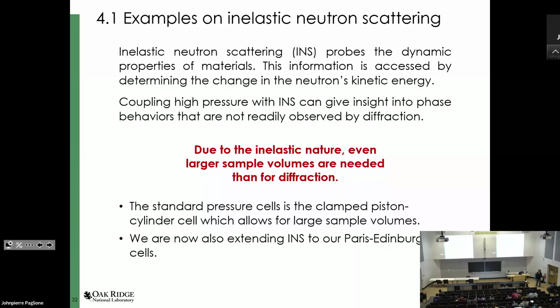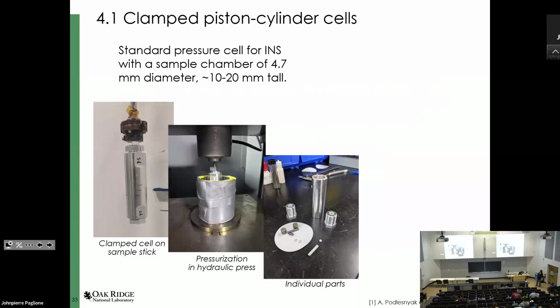But recently, there's also been development to push inelastic neutron scattering to the Paris-Edinburgh cell. These are large presses that can achieve up to 20 GPa, which is what I want to focus on. But before I get to that, I do want to briefly show you some of the things we are developing for the clamped cell. For those of you who have never seen them, these are piston cylinder cells hanging on a stick. They are pressurized inside a press. This is the nut you turn once you have applied the load. Here you see the individual components. This is a Teflon cup where you can put in your sample together with a pressure medium. And these are the carbide pistons that are used to apply the pressure to the sample.